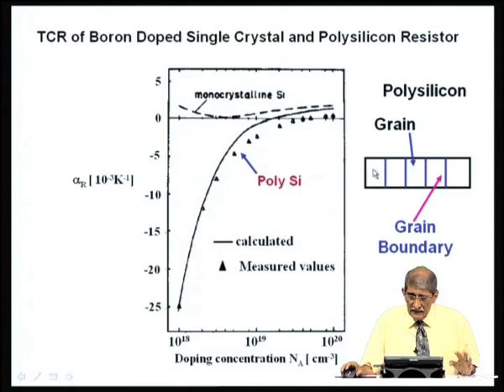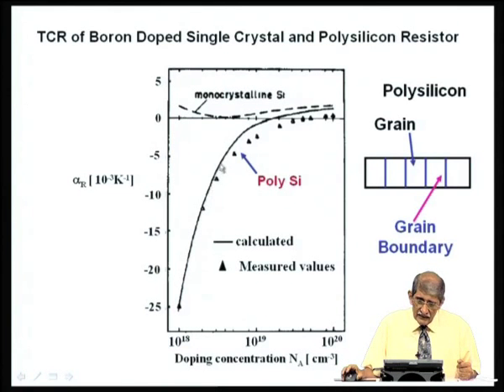There will be some barrier which will give the negative temperature coefficient, which is compensated by the positive temperature coefficient of the grain. So, you can see if you keep on increasing the doping, the temperature coefficient of resistivity will keep on becoming less negative, and it will approach 0, which would mean that I can adjust the doping in this grain and grain boundary and get a TCR, that is temperature coefficient of resistivity, practically 0 or negligible. That is what you are looking for in polycrystalline. That is the main advantage of using polycrystalline material. So, instead of single crystal resistor, use polycrystalline silicon.